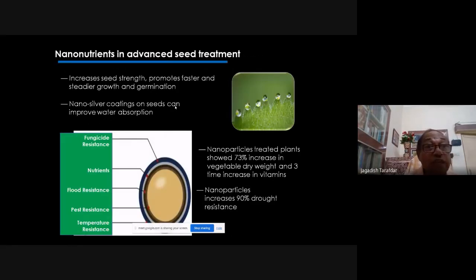Now, the nanofertilizer you can use from seed sowing to the grain storage. In every stage you can use this nanofertilizer. For example, if you use it as seed treatment, then it increases seed strength, and promotes faster and steadier growth and germination. Nano silver coating on seeds can improve water absorption. You see, when seeds are coated with nanoparticles, we found that they are fungicide resistant, they can take nutrient inside the seeds, they are flood resistant, pest resistant, temperature resistant. Nanoparticle treated plants showed 73% increase in vegetable dry weight and 3 times increase in vitamins. Nanoparticles increase drought resistance by 90%.